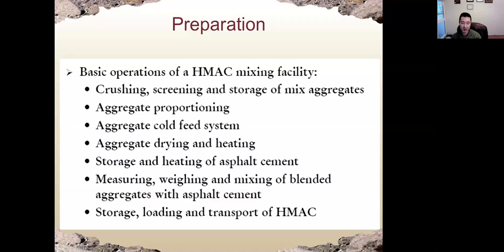Okay. And also a special treatment for the aggregate is drying and heating. If we have moisture on the aggregate, it will cause debonding or stripping of the binder from the aggregate. This is different from Portland cement concrete. For Portland cement concrete, we don't really care about making the aggregate dry. It can have some moisture, like wet condition or oven dry or air dry condition. We only need to do the moisture adjustment. But for asphalt concrete, we need to dry the aggregate. So this is one of the major differences on the aggregate side.